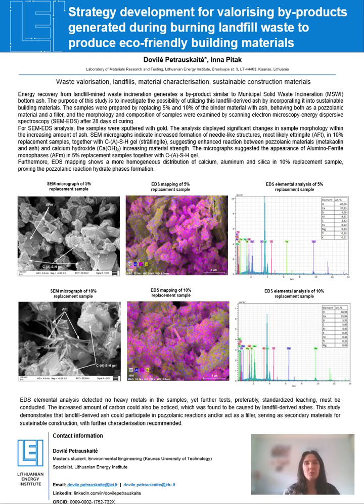So let's start with the 5% replacement sample, and the SEM micrographs show plate-like crystals surrounded by gel-like material, and these plates are consistent with AFm-type layered hydrates, aluminoferrite monosulfate phases, while the surrounding material corresponds to C-S-H gel, the main binding phase. So this indicates early pozzolanic activity.